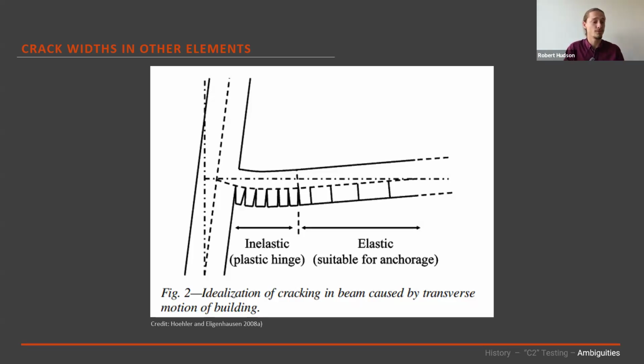The thing to be aware of from a design point of view is that if you're looking at a C1 capacity, fundamentally, you're allowing for a 0.5 mil wide crack maximum. If you are in a scenario where you're expecting cracks larger than that, your C1 capacity is not going to be a very good representation of what's going on. If your cracks are smaller than that, your capacity is going to be a little bit conservative. So keep in mind that when you're using C1 capacity, it's that 0.5 mil crack width.